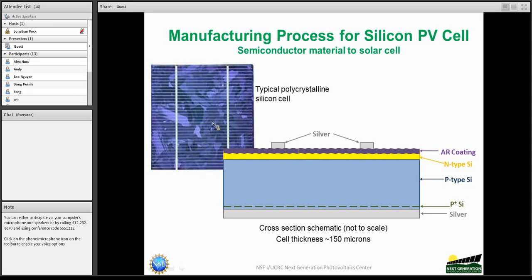A polycrystalline, multicrystalline silicon solar cell looks like this. There are many types of silicon solar cells, and here I'm just going to look at the multicrystalline silicon solar cell that is the most widely used, and it's a polycrystalline material. And here is a cross-section of the cell. Starting from the very top, you have the silver contacting the front. There is an AR anti-reflection coating. There is a small region of the silicon that is made N-type. The wafer itself is usually P-type silicon. There is a P+ doping put at the back that enables making good contact, and there is silver at the back, and that is the back contact.